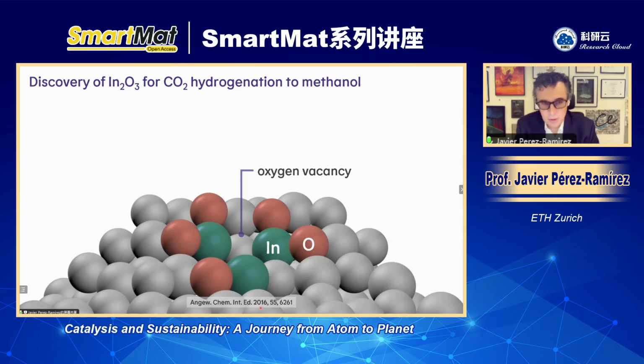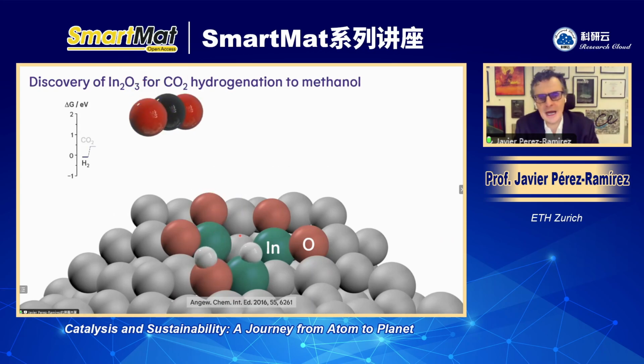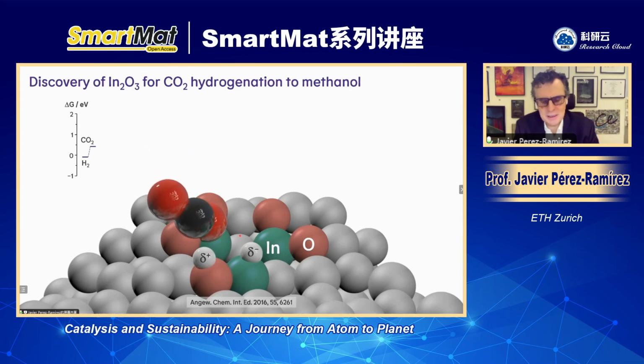And it relates to the fact that in order to do CO2 hydrogenation, we are using a reducible oxide where we can create oxygen vacancies in the material under reducing conditions of the reaction and at moderate temperatures in order for the reaction to take place. In these vacancies, what happens is that CO2 and hydrogen activate. So you have seen the heterolytic splitting of hydrogen on the vacancy, forming protons on the oxygen and hydrides on the indium atom, and the CO2 activates also in the vacancy.